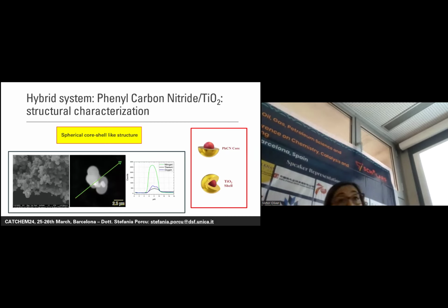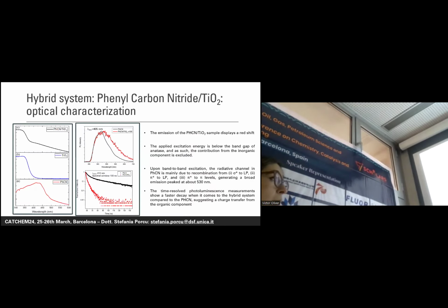And so we continued with all the characterization. From the morphological point of view, we did SEM analysis that showed a spherical-like core-shell structure, in which the core is characterized by the organic part, while the shell is characterized by the titanium dioxide. And then we continued with the optical characterization. And so we performed absorption measurements. I'm showing you this to understand why we found this material very important for photocatalytic application.